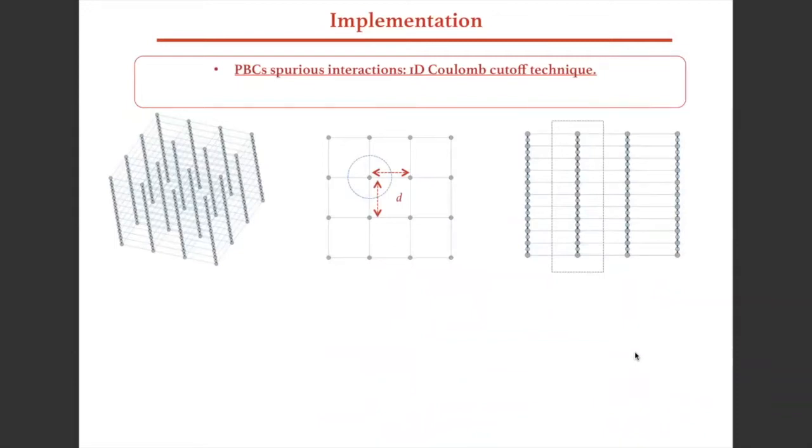So the idea is that most of the ab initio codes out there relying on plane waves rely as well on periodic boundary conditions. So basically, we are never simulating the 1D system on its own, but we are most likely simulating the 1D system plus a certain amount of vacuum and all the periodic replicas in the three-dimensional space. So this is, let's say, good enough for most of the properties we could be interested in, if we choose a vacuum which is large enough.